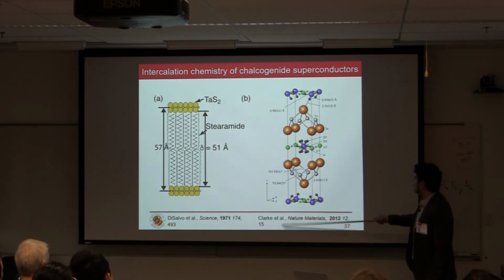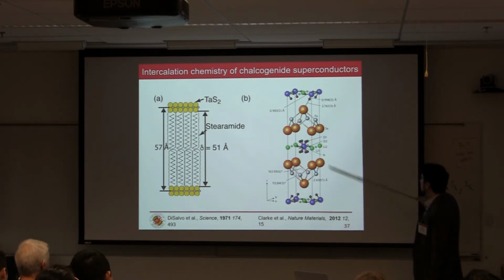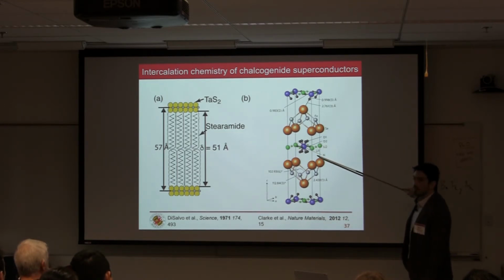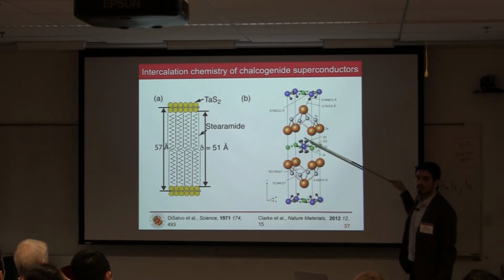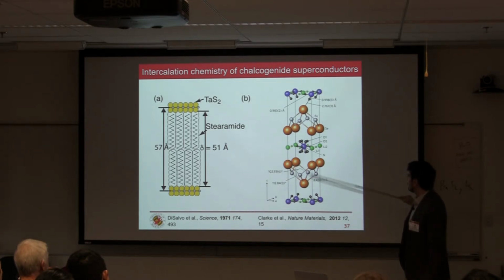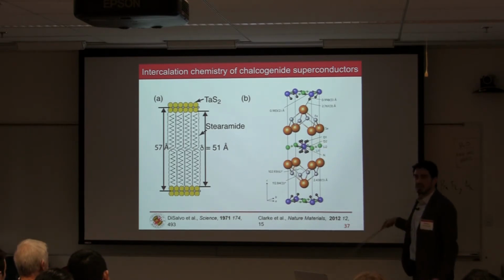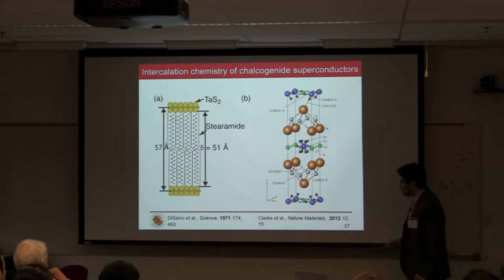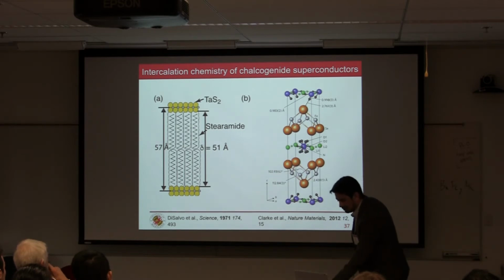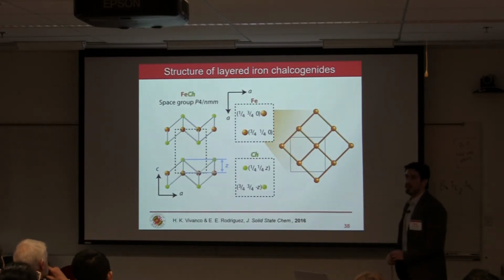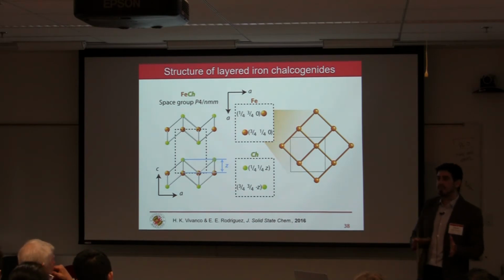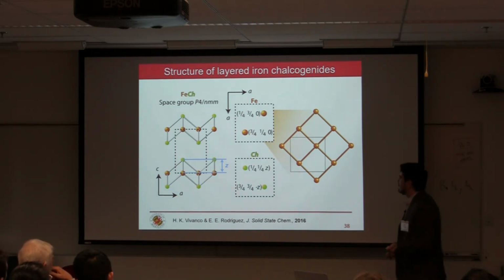And this is work of Simon Clarke more recently, where they intercalated lithium in liquid ammonia in order to raise the critical temperature of iron selenide from 8 Kelvin to 42 Kelvin. So it's a pretty remarkable technique. It not only charge dopes the iron selenide layer, but it also plays around with the crystal structure, so that it separates the layers apart. And so we were inspired by that to do similar chemistry in our lab. Now we're not going to use liquid ammonia. We're going to actually use water to do this intercalation.